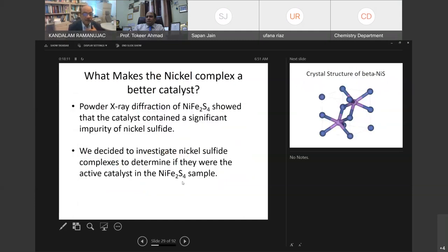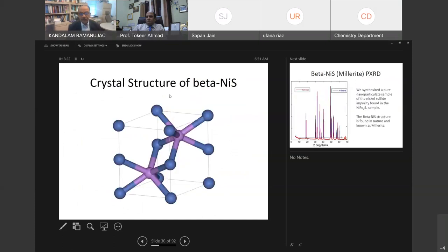All right. So then it started bothering us. Is the activity from NiFe2S4 or is it from beta nickel sulfide? Beta nickel sulfide has a crystal structure like this. There are edge-shared octahedral units of nickel, NiS6 octahedra. So that's a brief crystallographic segment.